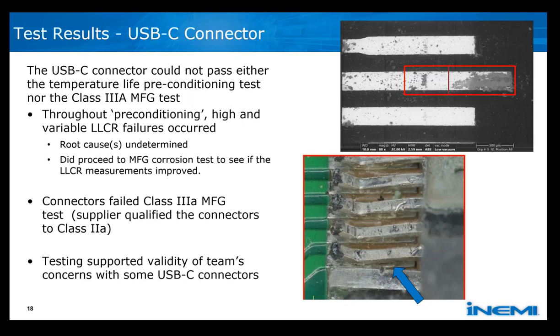More typical, and this is what we see with gas corrosion testing, is the top photograph. You see the three contacts. The longer contact in the middle has the red rectangular boxes. The lead-in during the mating of the connectors occurs from the right side to the left. What you see is corrosion product at the tip of the contact, right where the mating would begin, and that's the dark gray color material. And you see it's across much of the surface there in that right rectangular long box. That's not unusual at all for class 3A gas corrosion testing, where the corrosion product can creep along the surface and grow, if you will, along the surface.